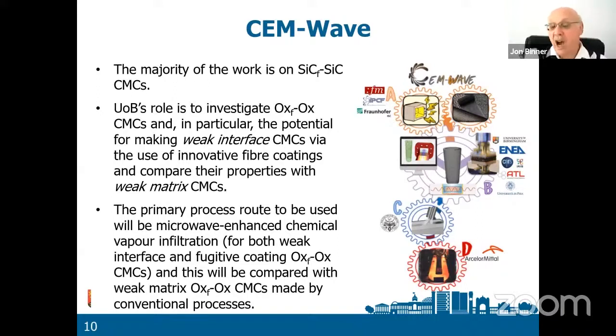And the way we are doing it is to use a process known as chemical vapor infiltration. I will say more about that later in this talk, and in particular using microwaves to heat the materials during chemical vapor infiltration. We're going to be having a look at two things in particular: the weak interface, that's our primary goal, but we'll also be looking at that fugitive approach, the third approach that I mentioned that not many people do. We will spend a little bit of time, not much, looking at that. And then we will compare our result with the more standard weak matrix oxide CMCs made by conventional processes. So by the end of the program, which is 4 years long, we should have a very good idea that either, no, you still cannot make weak interface CMCs, or yes, you can. Here are the properties, and this is one way of making them.